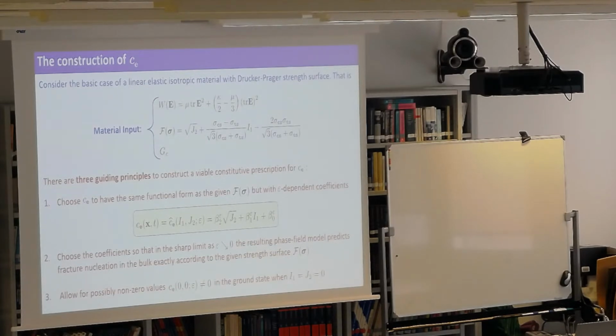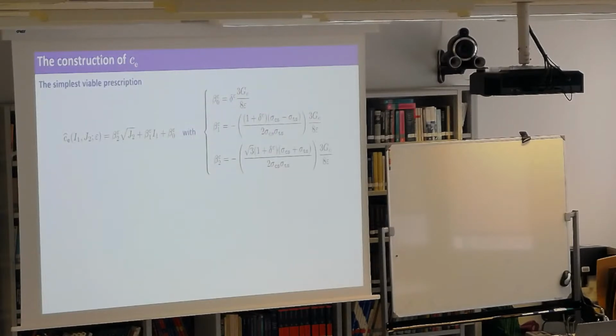And the third guiding principle is that you need to allow for the driving force to be possibly not 0 in the ground state. Even when you are applying nothing, you don't have to fix the value of this driving force to 0. And we need this, I'm going to show you now, because you need to espouse, and that's the difficult thing, how do you espouse strength, which is a surface in stress space, right, with GC, which is when you have singularities? How do you marry that, right? We're going to essentially come up with a formula that apparently does that, but again, it's not entirely clear yet that we can do it, and we don't have something very clean.